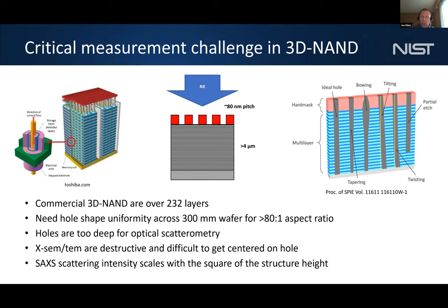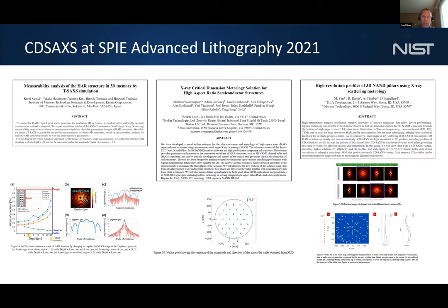And so they need ways of being able to measure and characterize this. In this particular case, the CD-SAXS ended up being kind of perfect because the scattering intensity scales with the square of the height of the structure. So when you're, say, 4 to 10 microns tall compared to the 40 to 100 nanometer tall FinFETs that we were looking at before, you suddenly are scattering 10,000 times stronger. This started being commercialized a couple years ago, but it was mostly small scale.